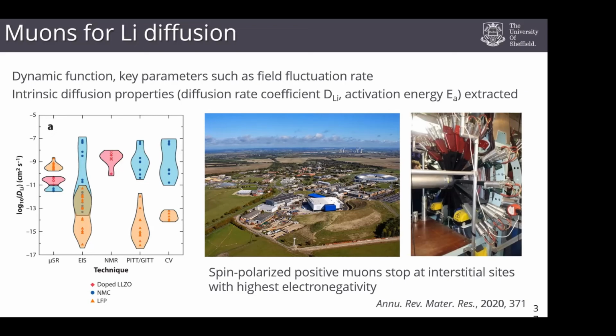Decayed, that's more correct. So it's a very sad experiment, but we collect all those positrons. They tell us what happened to the muon. That tells us what was nearby, and we can work out what the lithium diffusion properties are of that material.